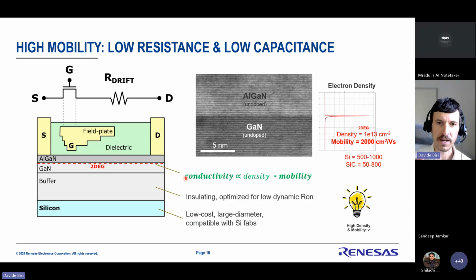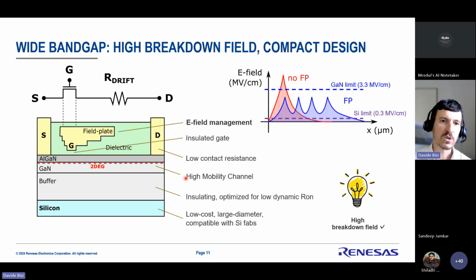Mobility is really a God-given parameter to GaN. And the second reason is, of course, the breakdown field. Being a wide bandgap semiconductor, we have a very high breakdown field of 3.3 megavolt per centimeter, which is 10 times more than silicon. Which means that we can pack the same voltage in a much smaller area, therefore again minimizing the resistance of that device.